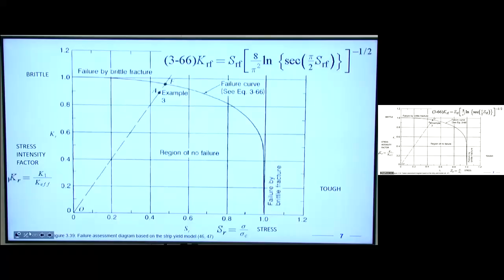So this was a very similar example to the one that we did in the last class, where we used linear elastic fracture mechanics, and we were determining things like what's the load we can apply so that we would make sure that we don't have fracture. And so in this case, if we choose a load of 50,000 pounds, apply it to that same type of bar, and we do not assume plane strain, but rather assume that there's a large plastic deformation because it's a little bit of a different situation, then we would find that we do not expect failure.